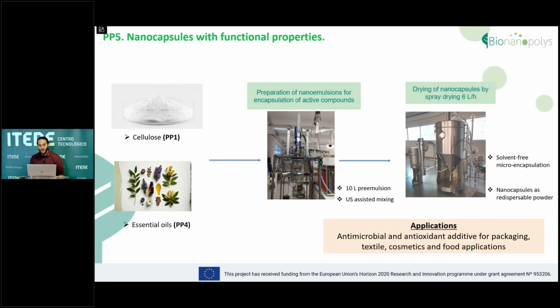On pilot plant 5, we would prepare nanocapsules with essential oils that would bring antioxidant and antimicrobial properties as well. This is done in a glass reactor of 10 liters, and the emulsification process will be carried out by high shear mixing or ultrasonic disruption. And then these nanocapsules that could be obtained in a liquid suspension may be dried using the spray dryer, which we have the capability to run at 6 liters per hour.